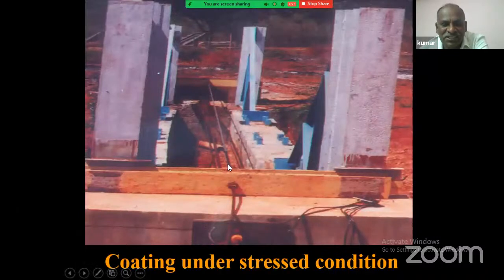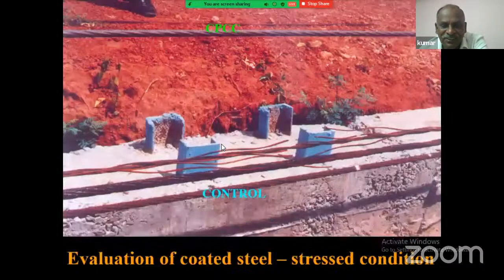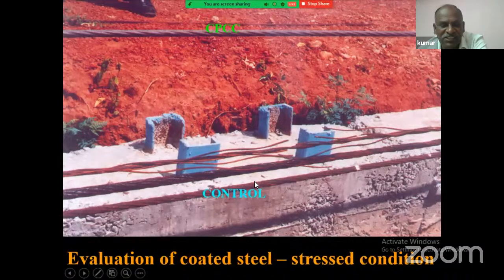This is the pre-stressing strand coated with CPCC. This was done at the beginning of the 90s. Even now, it is under stressed condition. You see that uncoated steel already snapped. You can see that the coated steel is still intact.